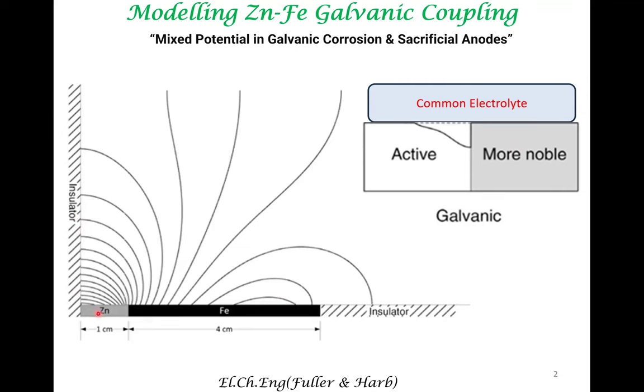This is a way to model the system. What is seen here is you have a smaller segment of zinc compared to iron. That is typically the case because the area of the anode that is getting corroded is much less than the more noble material. So here, this element is represented as zinc and this more noble metal is represented as iron. And then what we are seeing here is the potential distribution in the electrolyte. This structure indicates the electrolyte, and the other aspects — field lines and the interpretation of field lines — is similar to what you have seen in electrostatics from your high school.